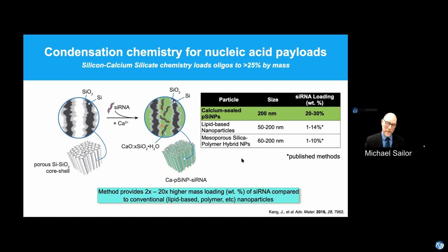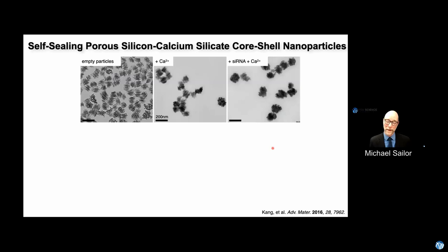What was really amazing about this, something that happened just a few years ago in our lab, is that the amount of nucleic acid loading we could get was much better than what had been seen previously with lipid nanoparticles or these silica structures. That was really formative for us. We had a way of loading a really high amount of nucleic acid into a particle. Of course, the more drug you put into a particle, the more potent it possibly can be. That's a really important factor and an important problem that we work on, and generally us here in the nanomedicine community. All right, so now I'm going to show you a couple of pictures of what these things really look like.